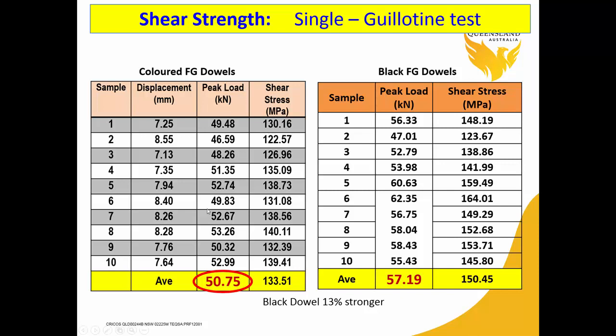The results of the test are tabulated in these two tables, for colored fiberglass on the left side and black fiberglass on the right side. The average shear strength for colored fiberglass is around 51 kN, and for black fiberglass is 57 kN. So black dowels are 13% stronger than those of colored fiberglass dowels.